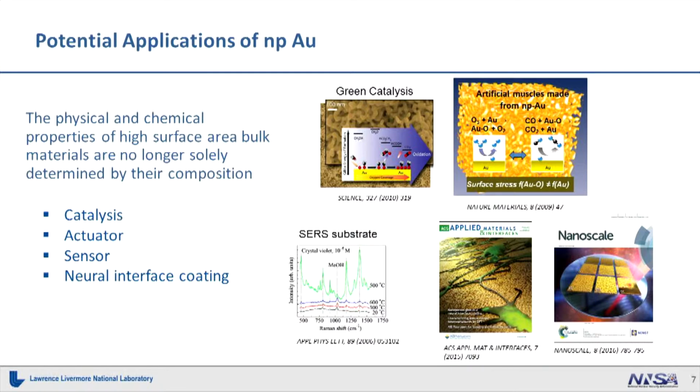We developed a method to create nanoporous gold libraries on a single chip, and these libraries consist of nanoporous gold patches with different feature sizes that are produced by localized laser heating. And using these nanoporous gold libraries, we're actually able to do parallel studies of cell material interactions to study the structure-property relationship.